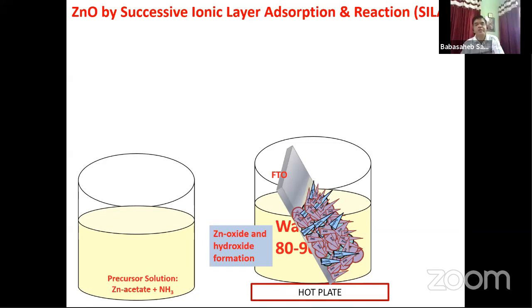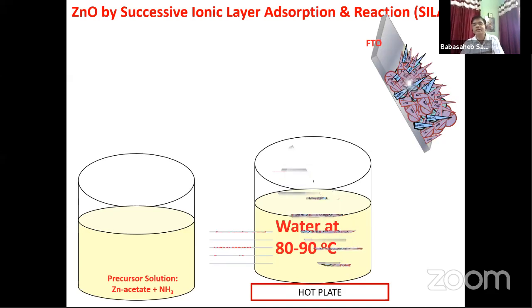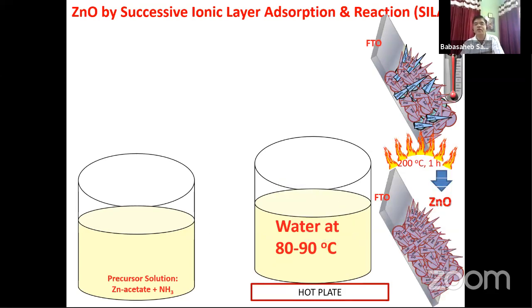But for the dye-sensitized solar cell, you need pure zinc oxide, so it should be free from hydroxide formation. In order to get rid of this hydroxide, we optimized the annealing temperature and dropped it down to 200 degrees Celsius. So we have annealed that film at 200 degrees Celsius for 1 hour so that you can get pure zinc oxide on the FTO coated glass substrate.